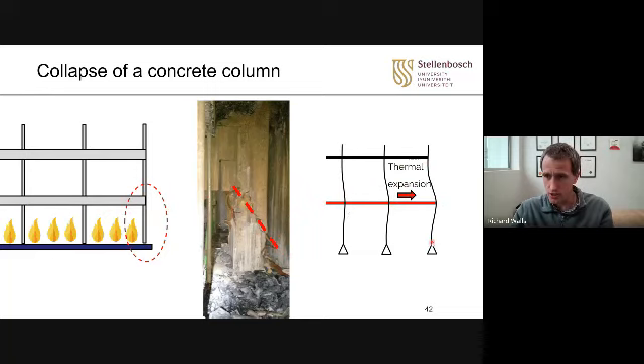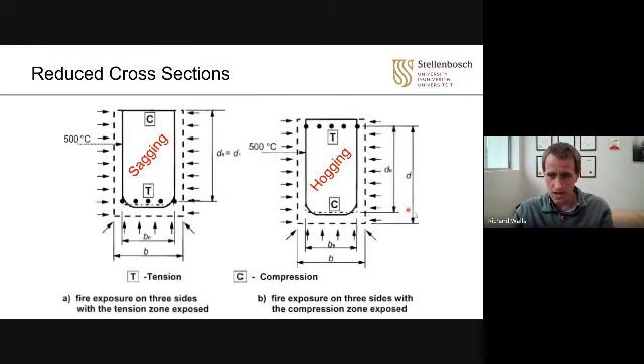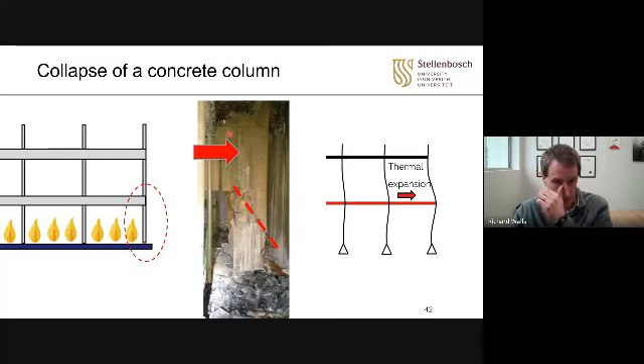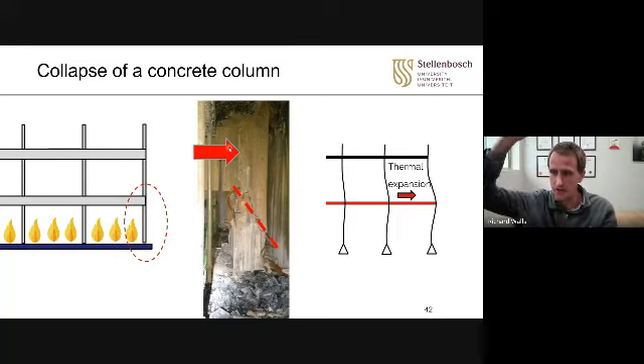And it was an edge column here that failed because there was a retaining wall and there was nothing holding it back. So if it had been fixed to the retaining wall, the retaining wall to hold it wouldn't have come down. Push, push, push, and to the point it actually failed this column because this was about a 400-ton lateral force. So it's the weight of about 400 vehicles sideways. So you can imagine a cable hanging 400 utility vehicles, small trucks, and that would be the sideways force this beam exerted and failed this.